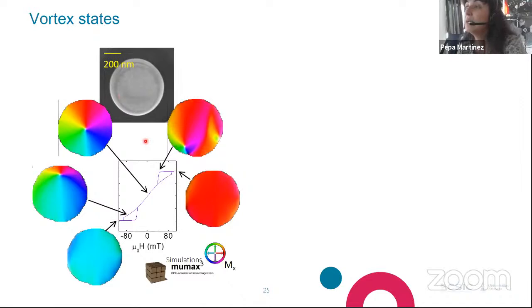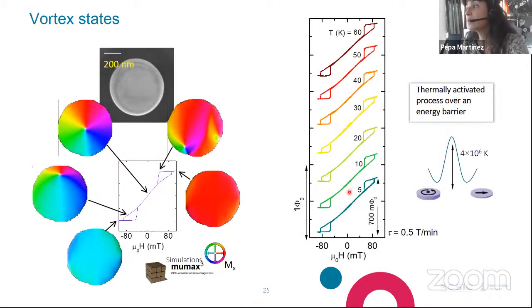And this, what you see here below, is the hysteresis curve that has been obtained by means of numerical simulations, okay? Experimentally, using our nanosquids, we find this kind of hysteresis curve that, as you can see, reminds quite a lot of these numerical simulations and makes us confident that we are stabilizing, nucleating, and annihilating magnetic vortices here in the squid. As you can see, these measurements can be obtained at a really broad range of temperatures, up to 60 Kelvin. This corresponds, let me remind you again, to measurements performed on one individual magnetic disk, okay?